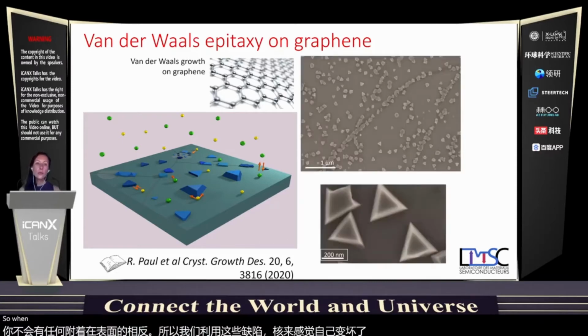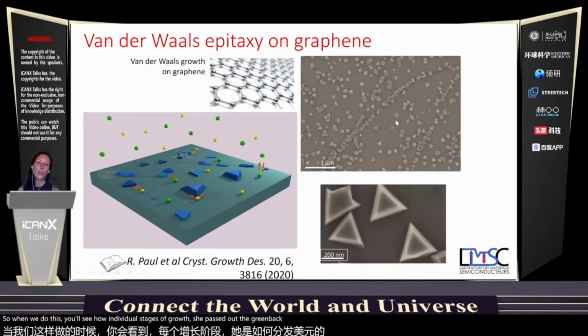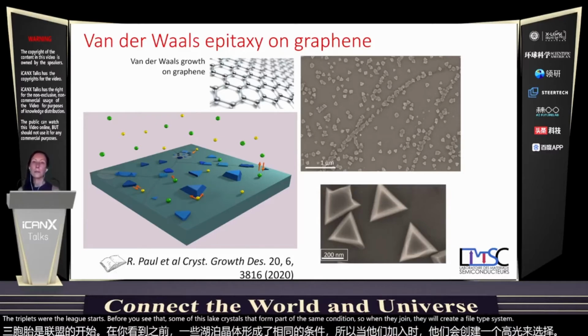So when we do this, you see how in the initial stages of growth, the grain boundaries and some point defects are the initial points where the layer starts to form. You see that some of these crystals that are formed are in the same orientation. So when they join, they will create a highly crystalline layer.